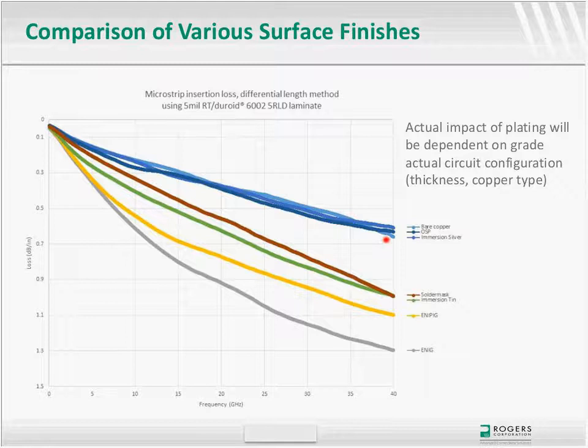We're seeing more and more people trying to adopt this, particularly when designing in the 70, 77 gigahertz frequency bands. Then you have what happens with immersion tin, which I think we're finding more commonly than electroless nickel immersion gold, which is the gray line here. And then something here called ENEPIG, which is electroless nickel, palladium, and immersion gold, but it's got phosphorus as well on there. And so you can see the differences that happen.